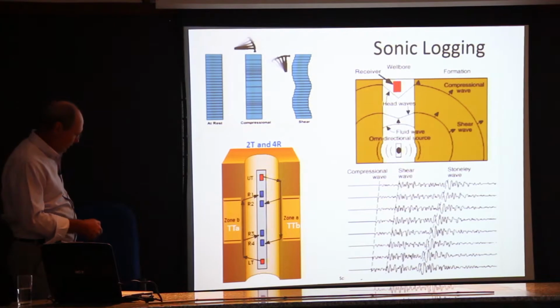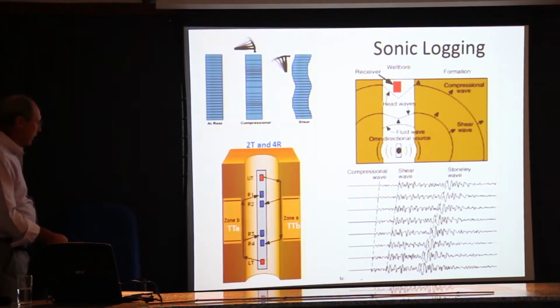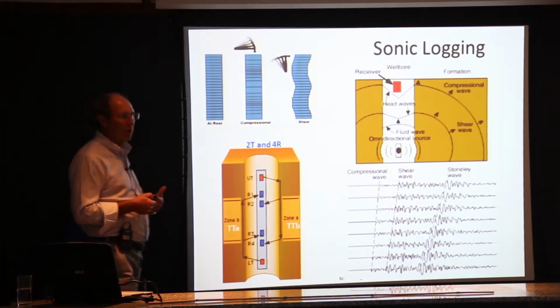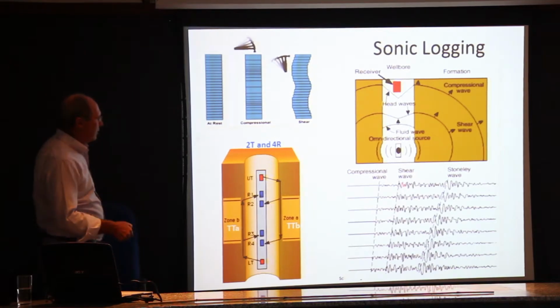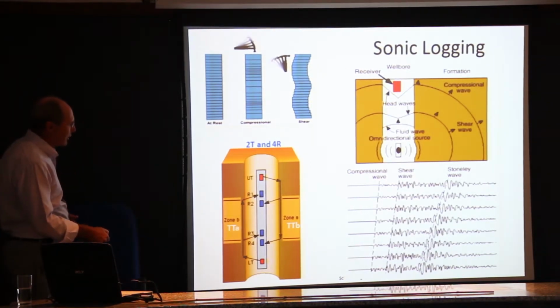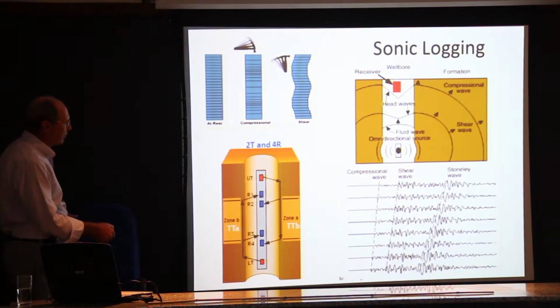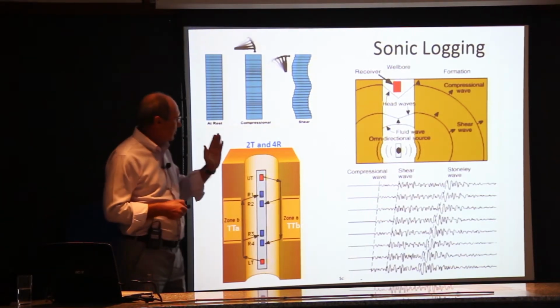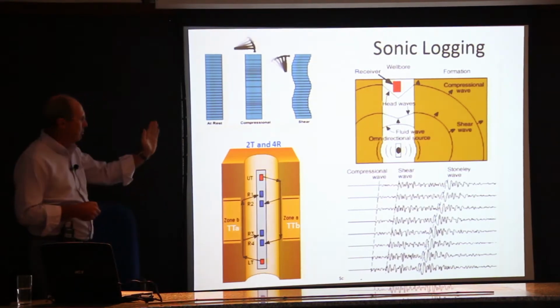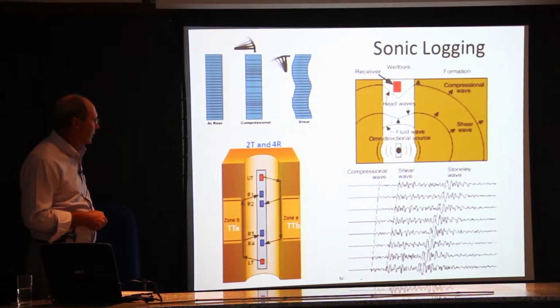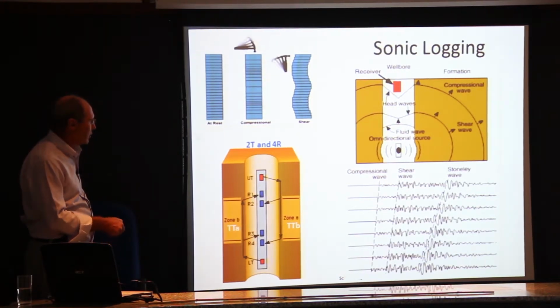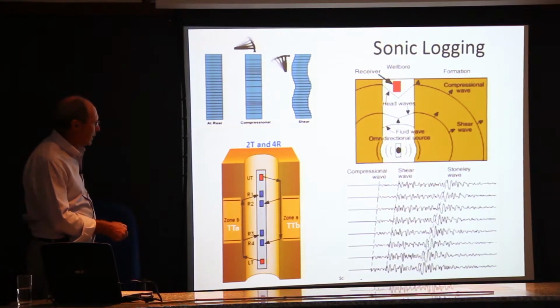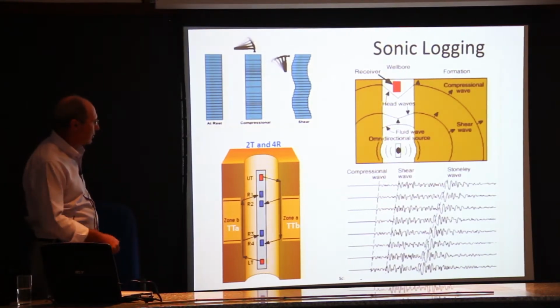So the older sonic tools were very simple. You had one transmitter and two receivers here, another transmitter, and you would actually use very simple interferometry to come up with the travel times. The newer tools actually use semblance processing. The latest tool actually has 13 receivers, so you can do semblance type processing over that entire receiver array to get the velocity and the slowness in terms of the move out, just like you would for seismic processing. And by using semblance processing, you can solve for the compressional arrival, both the fast and the slow shear, and also the Stoneley wave.